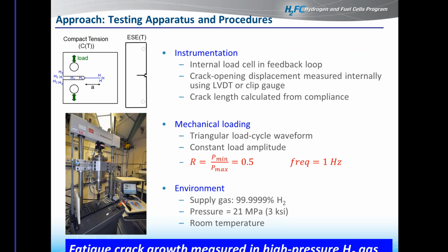That's what we're really trying to simulate by this. The frequency that we tested at was 1 hertz, and this became a balance of testing at lower frequencies. We've observed that the effects of hydrogen can be more dramatic or more enhanced, but really it's an optimization, because testing at lower frequencies obviously requires a larger amount of time for the test to complete. So that's the parameters that we settled on for the majority of our tests.